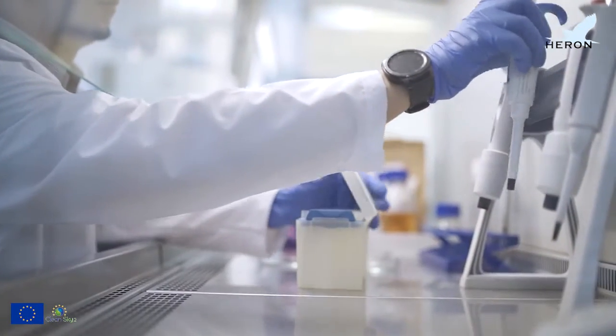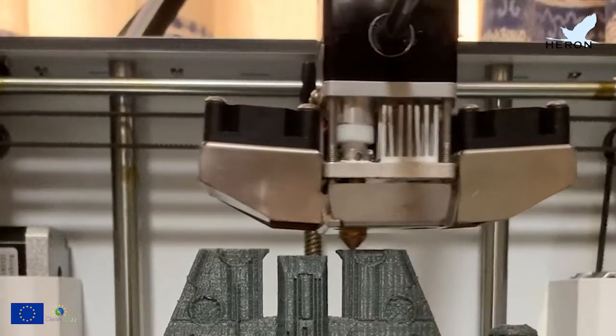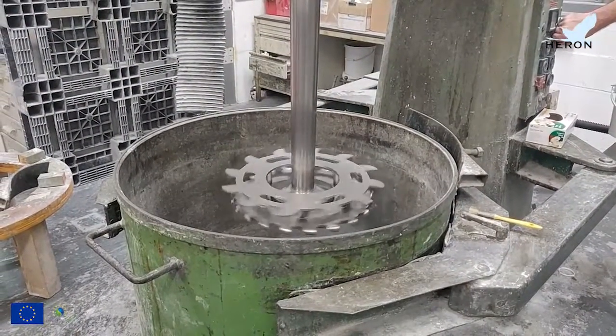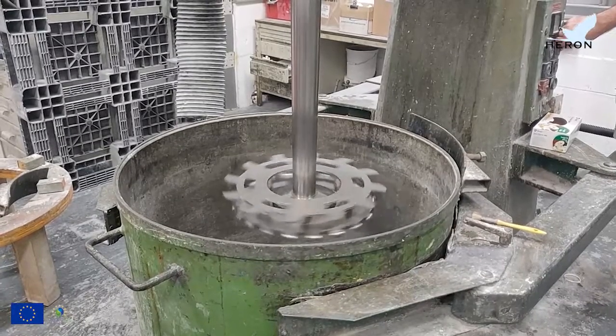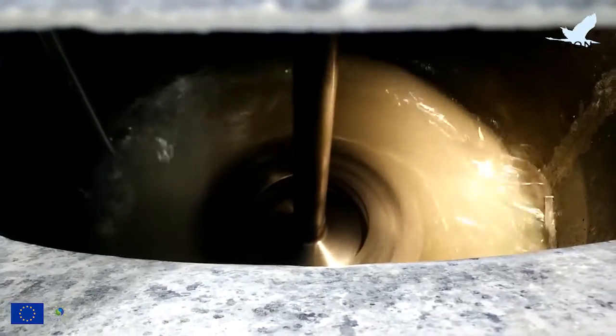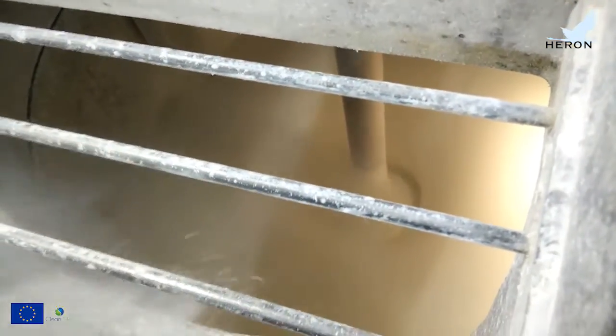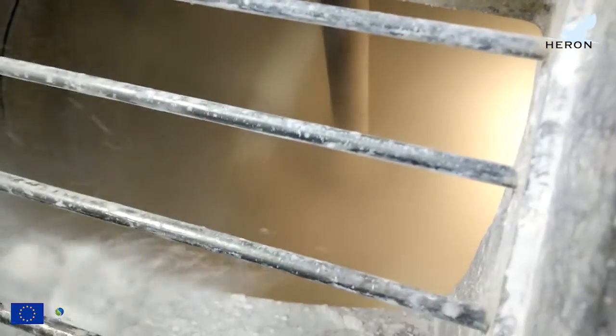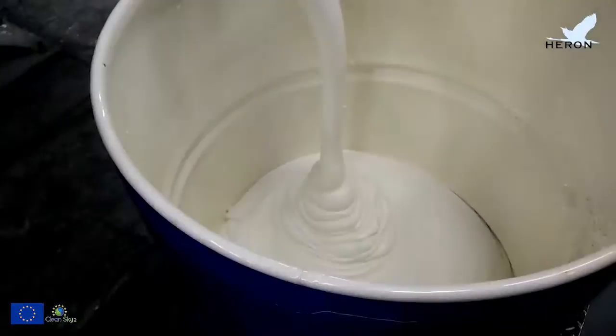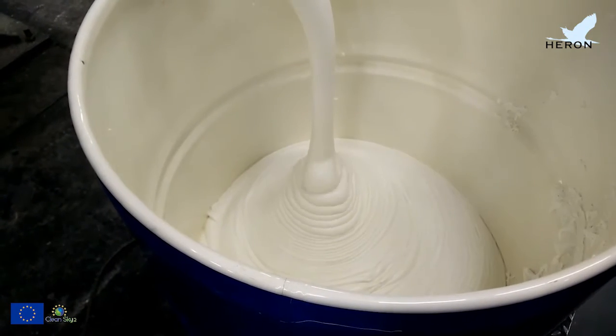Alchemy formulated a two-component polyurethane system suitable for 3D printing large components. For the manufacture of both PU3721 components, a high-shear vacuum dissolver fitted with a two-step dissolver blade was chosen. The first stage is to mix the liquid components, followed by the addition of the fillers, and finally the lightweight fillers and additives. Here we can see that the blade is ideally suited to efficiently mix the lightweight fillers used in PU3721. The final stage is to decant the material under pressure into the appropriate container.